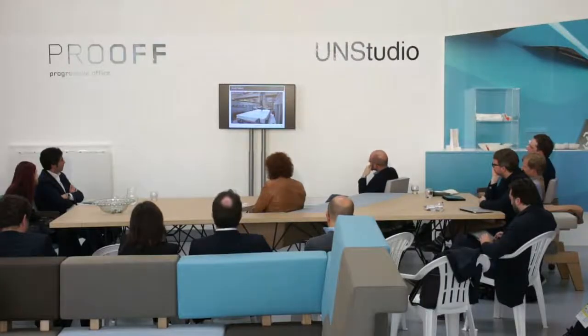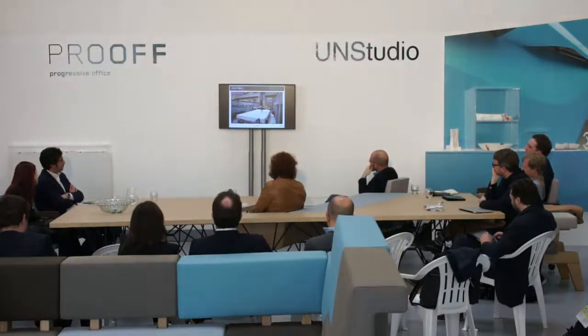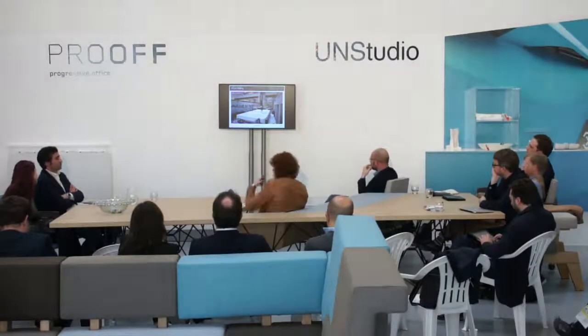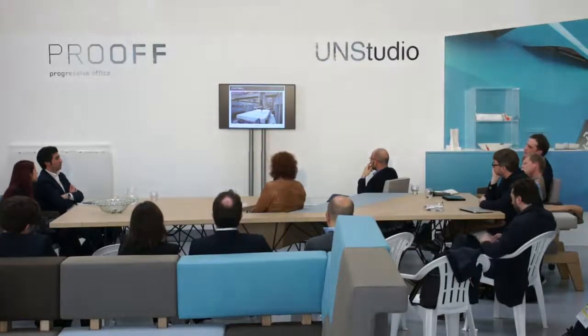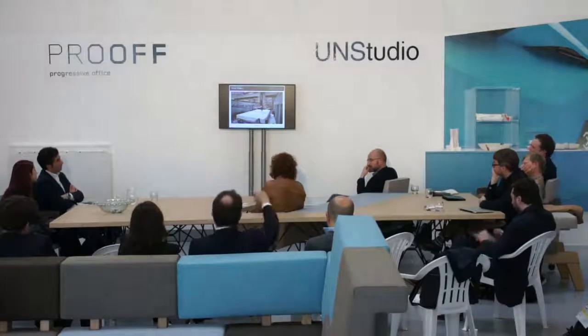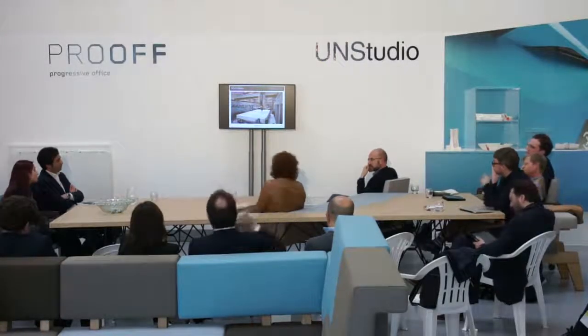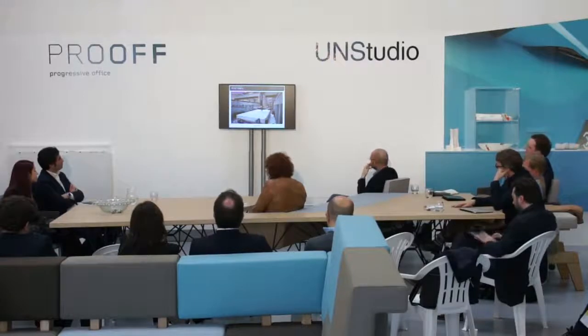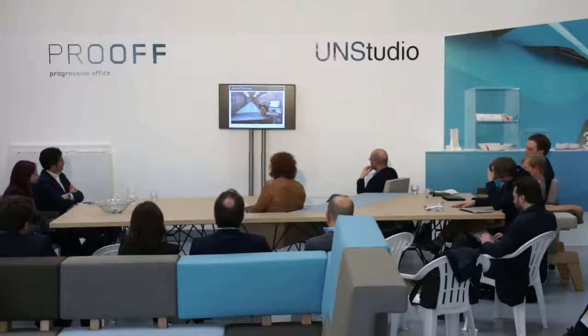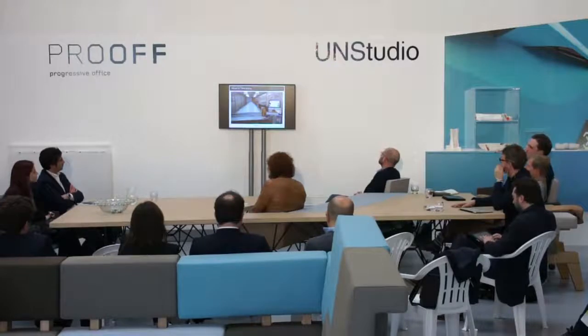This is a mold which is 8 by 4 meters in size. The milling machine is 28 meters long, 8 meters wide, 3 meters high, basically the Z axis. This allows us to go for extremely large elements. We are actually limited by the transportation rather than fabrication. The cutting of the fibers is quite expensive. It is also CNC supported. That means you reduce the wastage of the materials. And again, this is a cost-saving factor.